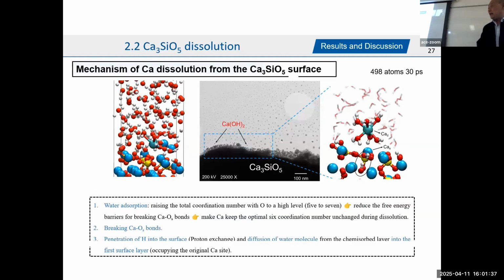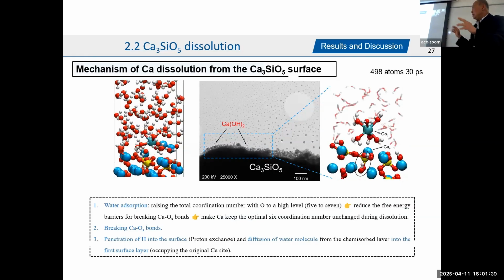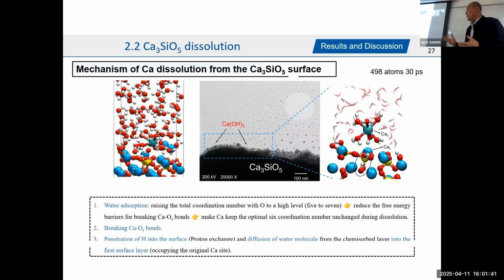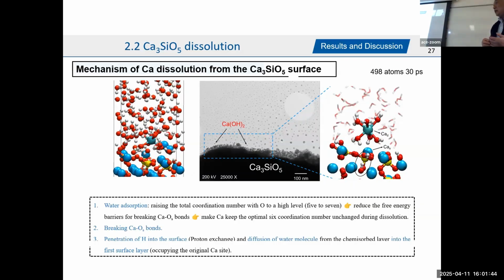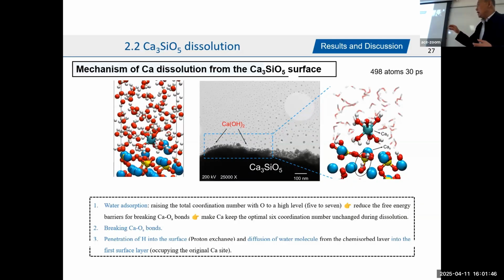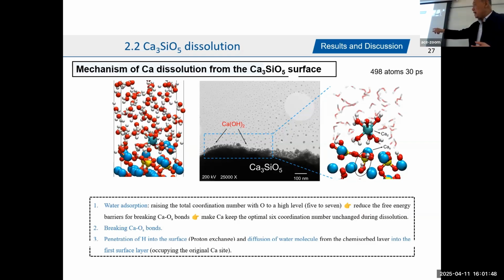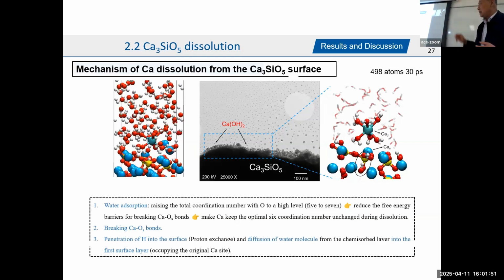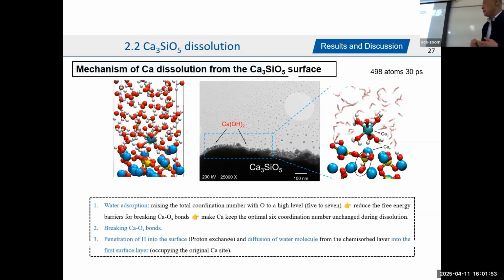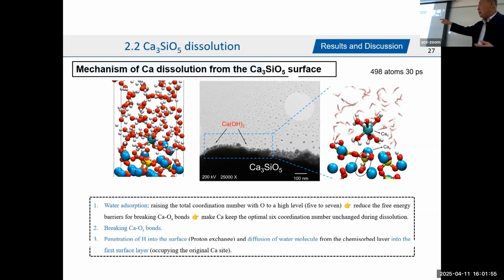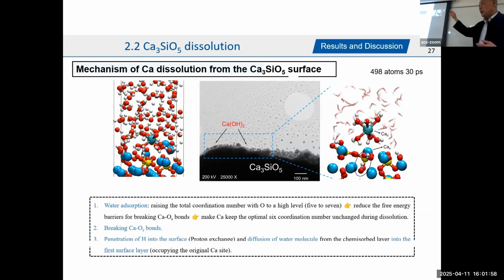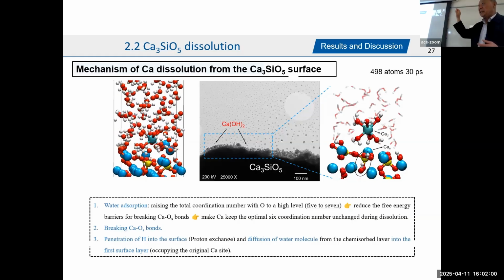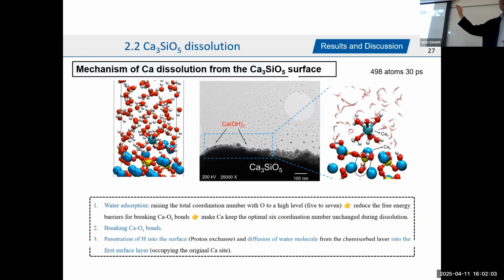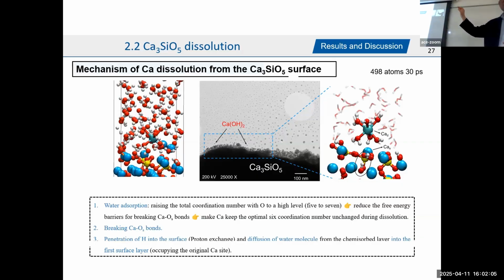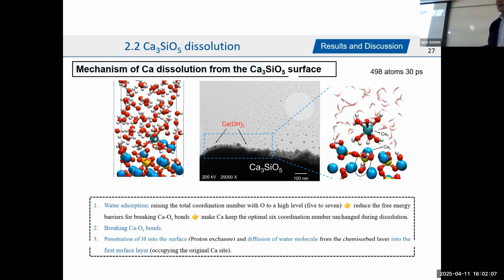So here we showed, in the center we have one that is very nice. You see the TEM photo. Basically you can see the black one is the particle of C3S, and away from it there are a lot of black spots. So that is the calcium hydroxide. So this is a kind of verification from experiments.